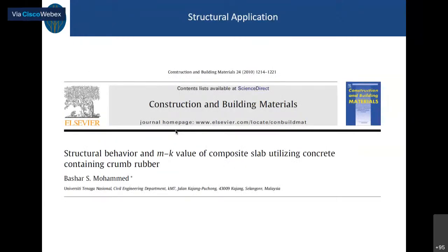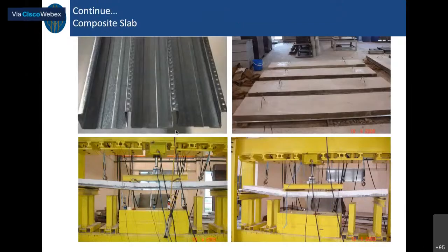And also we did a study using it in the composite slab. In the composite slab, the topping concrete is usually very rigid, and the steel sheeting is very ductile. So due to incompatibility, under a very low load, it will break. But when we use rubbercrete, because it is ductile, it has some flexural deformation without breaking. So when we use it as a topping material for the steel sheet in the composite slab, it will enhance the load carrying capacity of the composite slab.